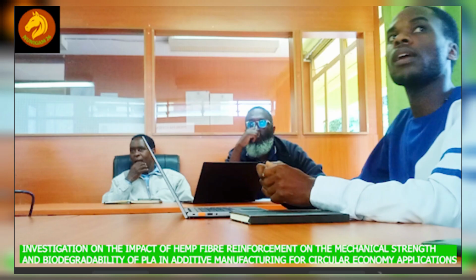Composite preparation: I will have 3 samples in the Taguchi method. Blend PLA with hemp fiber at 10, 20 to 30%. Extrusion using extruder parameters like temperature between 200 to 210. For the Taguchi method or design of experiment, we will take 1 sample of 10% hemp to 90. We will first take 10%.